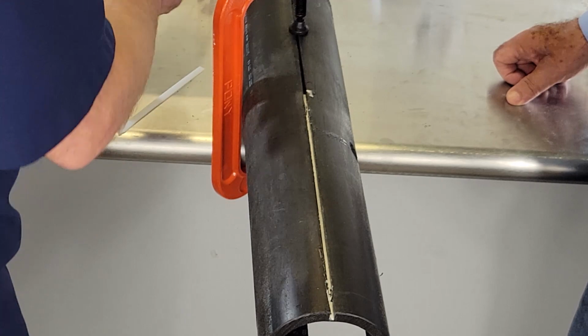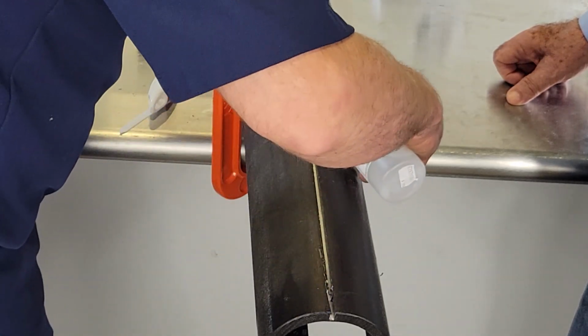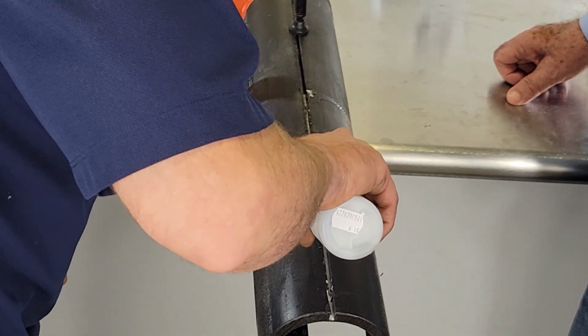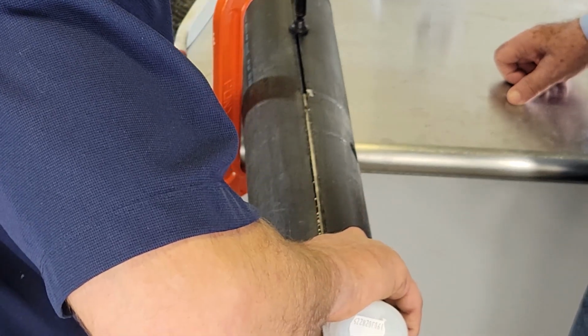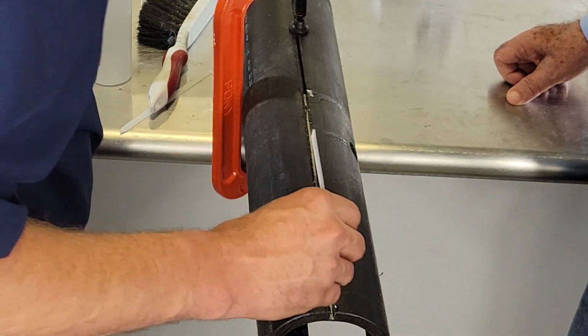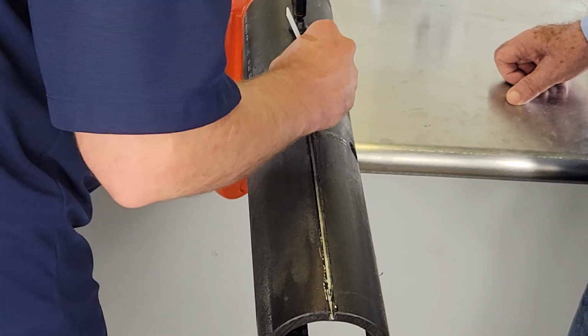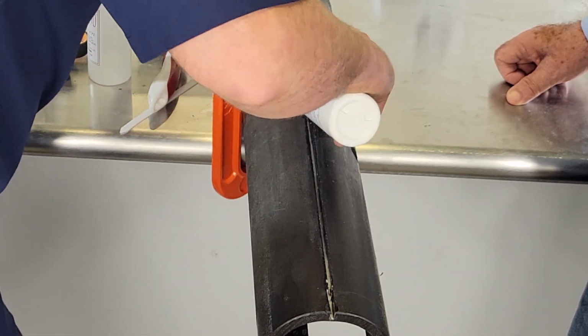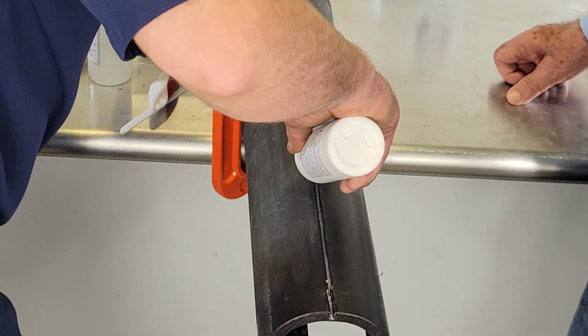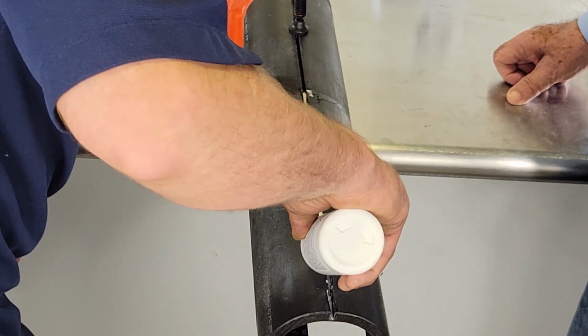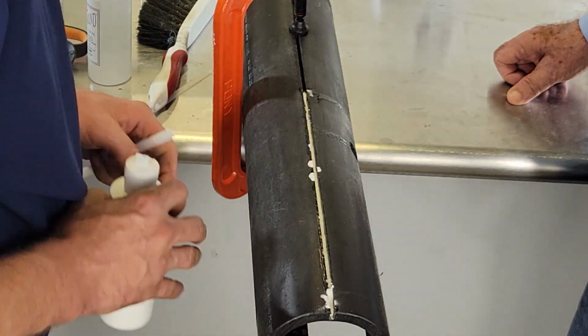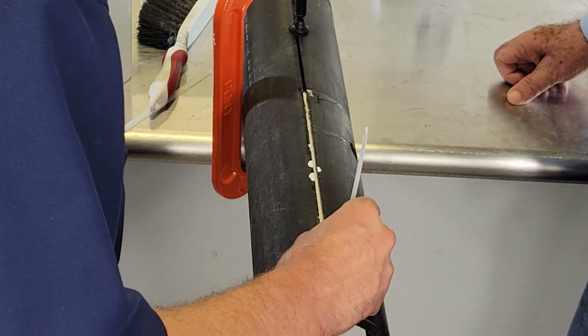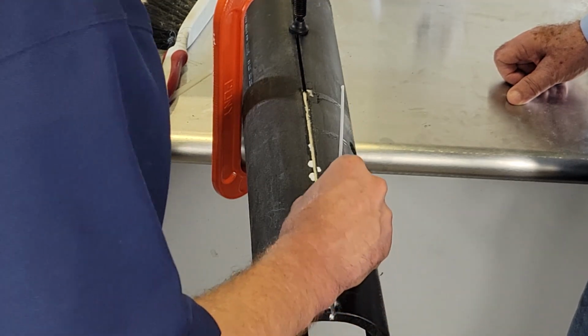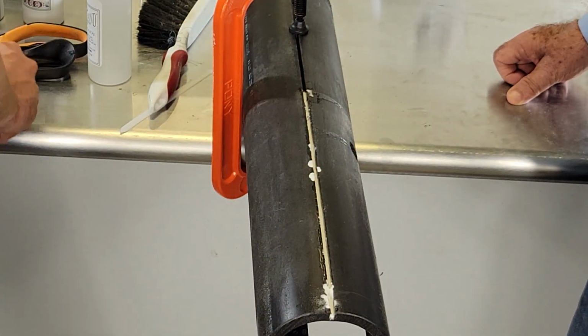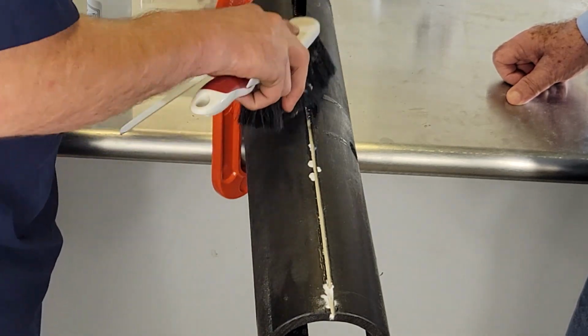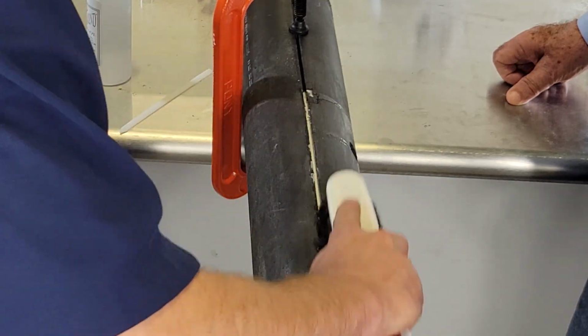All right, our second application, the SI green. Spread it. And sprinkle the filler on. It's a squeeze bottle, so you can squeeze, make sure you get enough. If you get too much, you can just brush that off. Now, it sets quickly. We'll give it a few seconds before we use the brush again. Ray is spreading it. If the filler has not reacted with the adhesive, the poly filler, it will brush right out, which is what you want to have happen. That's 2 coats.